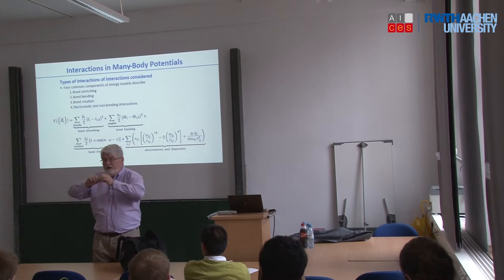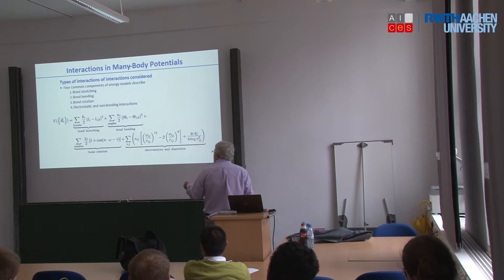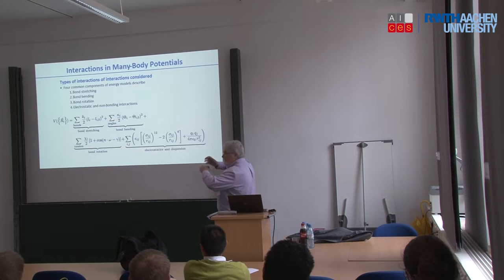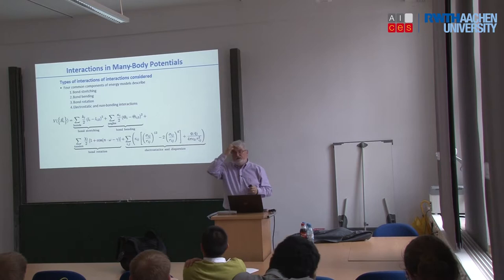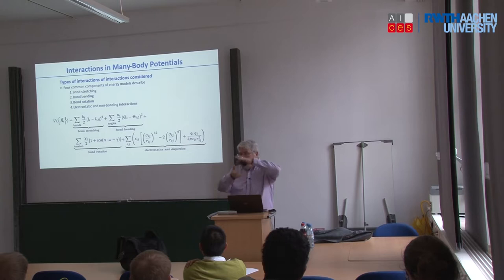And then you can have stretching terms, which just says the energy. This is a Hooke's law stretching term. This is a bending term to do with bond angles. Here's bond rotations, and here's the electrostatics. So this would be for something like a polymer type structure, where you don't necessarily expect any rebonding. You're not looking about breaking, but you're looking at the configuration of this, maybe the way this thing curls up. Sort of thing you might do in protein folding type simulations.